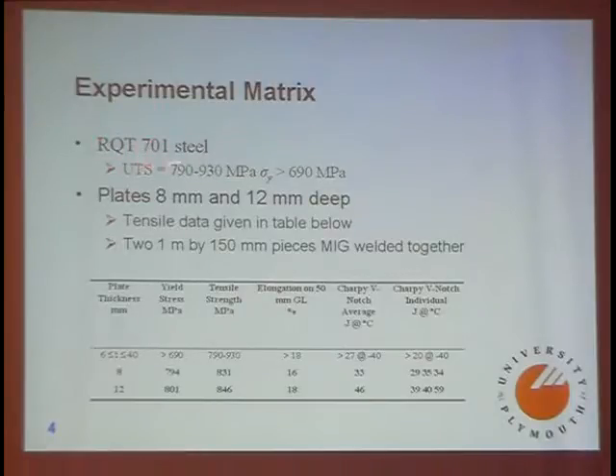It's a high strength steel. It's called a 701 normally because it has about a 700 megapascal yield strength. And I used plates, supplied by Corus, 8mm and 12mm thick, and we welded together two plates a meter long by about 150mm wide using MIG welding. These plates have slightly different properties, but they are actually significantly higher in yield stress than the stated 700. So you're up around 800 megapascal yield as manufactured. So these are actually high-strength steels.